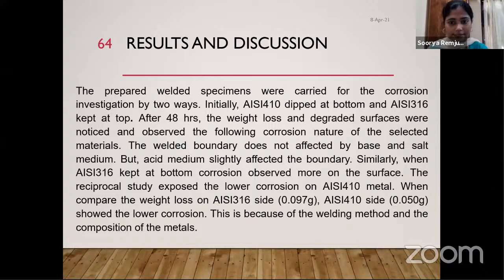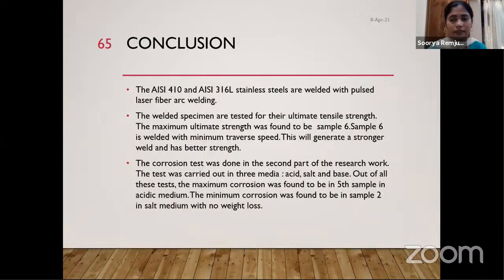Now for results and discussion, we can observe that with differential aeration, when you keep 316 at the bottom, it will corrode much higher than the 410 steel. So for mechanical purposes, or when you go for application-oriented use, you should keep the 410 steel in contact with the medium, whether acidic, base, or salt, or whatever the medium is. The 316 should be kept on the other side. That's how it has to be kept.